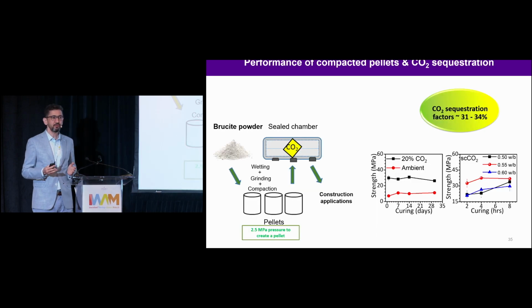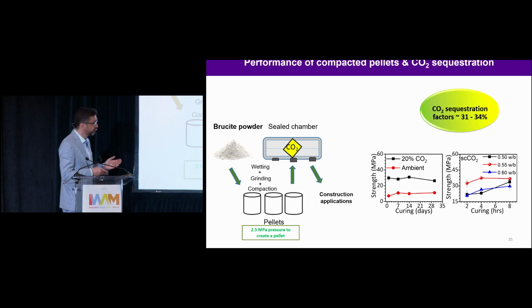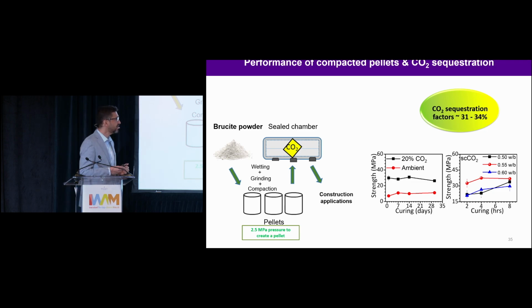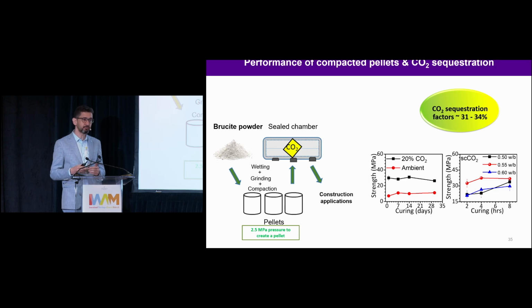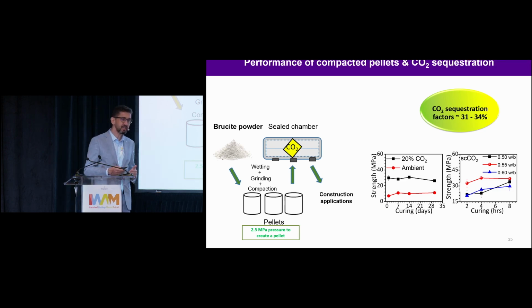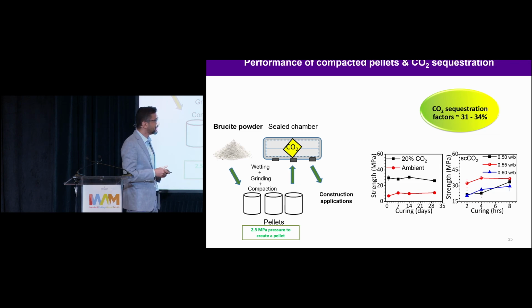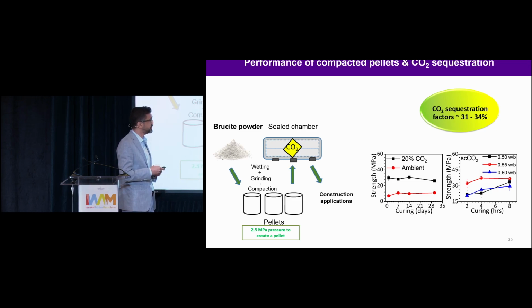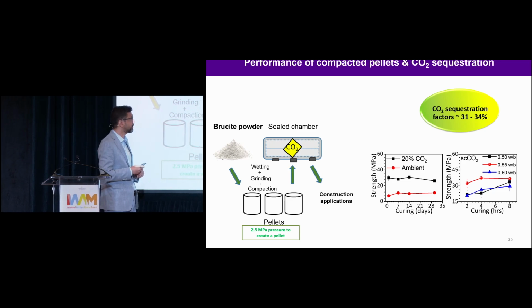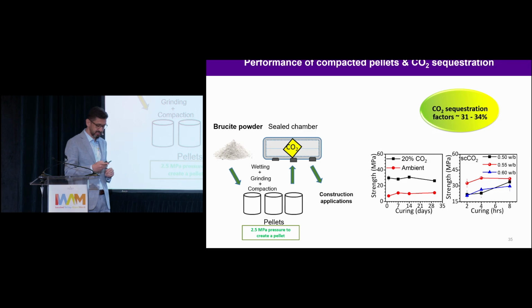So, as an engineer, we have to look at how strong these materials are. After curing, as I mentioned previously, we have significant strength gain in the magnesium-based cement, but we need to wait around 3 days, 7 days to gain this strength. And for the precast concrete industry, we need to accelerate the production cycle to an hour, for example. So in this case, supercritical condition will be much more useful. In 4 hours, for example, we are reaching around 40 megapascal, slightly above the strength of the accelerated carbonation condition, and the carbon sequestration factor is around 30 to 34%.